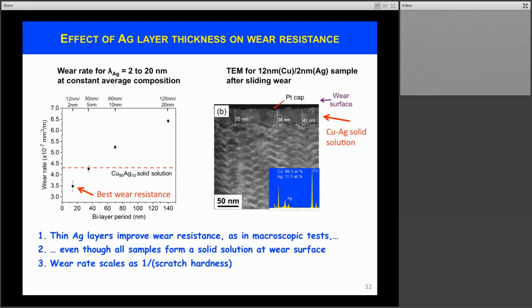When we look at the microstructure in cross-section by TEM, we see that the multilayers are still present, but close to the surface, the plastic deformation has forced the formation of a copper-silver solid solution. Nevertheless, these multilayers provide better wear resistance, because if we start with the solid solution to begin with, the wear resistance is lower. This is the red dashed line here. And so this microscopic testing helps us illustrate the fact that interfaces, chemical interfaces, do promote wear resistance.